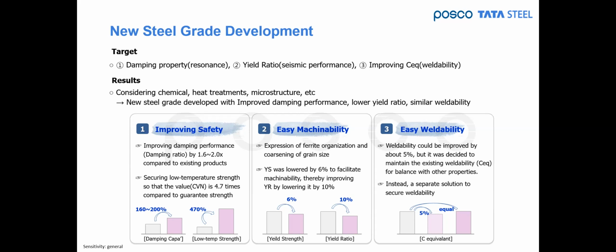So if we go into the details a little bit more, improving safety was an issue from two sides. One was damping. Currently, compared to the regular S355s, the new steel grade has about 1.6 to 2 times better damping ratio. Along with that, we wanted to add low temperature toughness, which is about 4.7 times compared to the regular S355s. Meaning, in the actual performance of the Hyperloop tubes, you see a lot of vibrations, which will lead to fatigue, so better damping will help with safety. Also, wherever Hyperloop is built around the world, it will go to regions with very low temperature, so that also will improve safety.